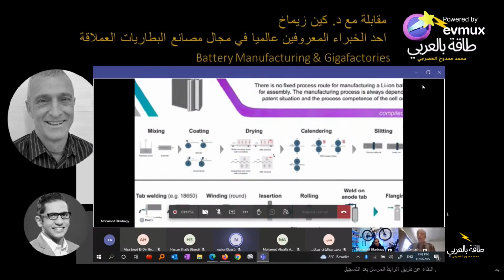So you have this transport problem where water molecules are moving up through. And what they do, because the binder is dissolved in them, they effectively drag the binder up with it. And if you dry your electrode too fast, all of your binder, your CMC and your SBR in this case, when you're finally dry, most of it's up at the surface and not a lot of it's down at the bottom. And if your SBR is moving up to your surface, well, the SBR is what holds your electrode to your foil.